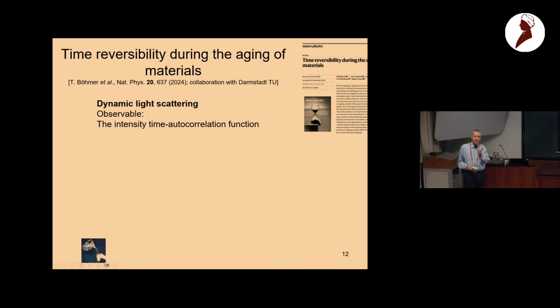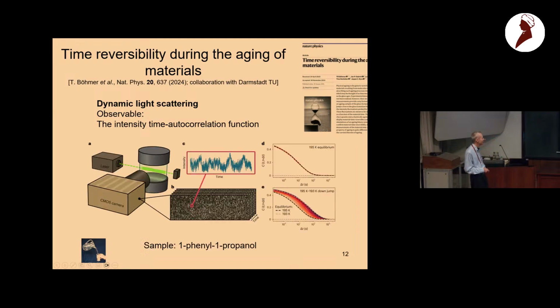And what we would like to measure is the ensemble average time autocorrelation function during aging. Usually in equilibrium in dynamic light scattering, you simply get good statistics by having a moving time window like this. But you cannot do that during aging because things are changing, so you need to do an ensemble average. And the solution is to use a camera, which Luca is also doing some of his experiments. So we come in with a laser here and look at the scattered light and take 20 or 10 pictures per second and do that for 1 or 2 days. You get a lot of data.